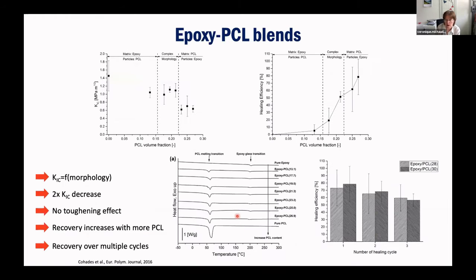So we understood a bit how it works. We also looked at the toughness of these materials, and we saw that indeed from the epoxy to epoxy plus more and more PCL, the toughness, K1C measured by TDCB in this case, decreases progressively. And when you get these PCL matrices with epoxy particles, you have quite a low toughness. But the healing efficiency, of course, does the contrary. At the beginning with pure epoxy or very little PCL, you have no healing efficiency, and then it increases. And so the toughness recovery is almost complete when you have already maybe 25–30% of PCL in volume.